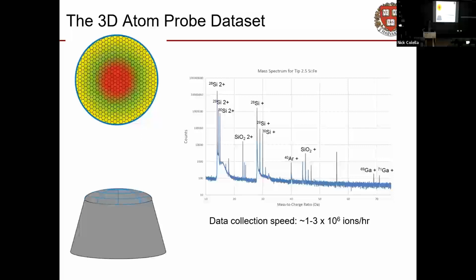Yeah, it's not high enough to tell the difference between a proton and a neutron, which means there are some elements and some isotopes you can't separate, like iron-54 and chromium-54, which differ in mass by the mass of an electron, which is too small. We can't measure that. But almost everything else can be measured. And conveniently, this technique doesn't discriminate, by which I mean it doesn't care what kind of atom you're using. This works for hydrogen, this works for uranium, this works for everybody in between. Anything at all, lithium, all those things that are really, really hard to get measurements of, beryllium, whatever, they all are grist to our mill, we can measure anywhere.